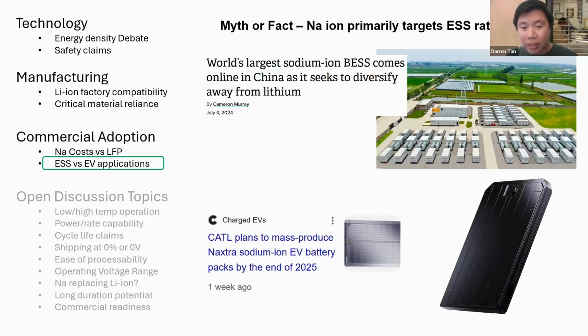Next question is from Michael Perron. Curious on your take on the Stanford study noting problems with degradation of sodium-ion batteries faster than LFP. I don't know this study, but from our own results, as a company, we buy a lot of LFP cells from different commercial sources, and we compare them with our own batteries and also commercial sodium-ion batteries. We found that LFP is great within the Goldilocks zone. So LFP is like a little baby. You just keep it never too hot, never too cold, never over discharged, never charge too fast. It will run very well.